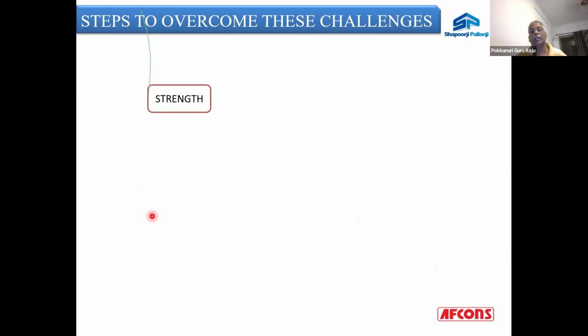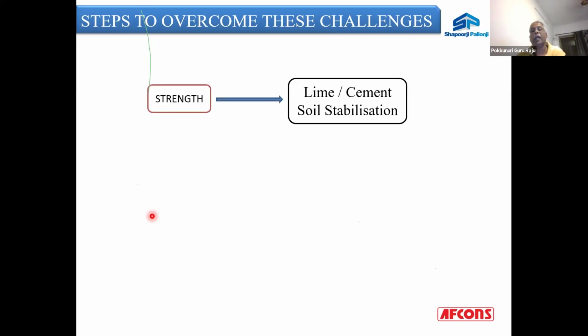Now, if it is only strength, you can deal with it using lime and cement stabilization or any other mechanical or chemical stabilizations like fly ash. But in the case of black cotton soil, strength is not the only criterion which is low. It is the nature of the soil, which is expansive. I need to address this expansiveness also if I want to achieve the outcome of the soil stabilization as the perfect, suitable, or approved one.